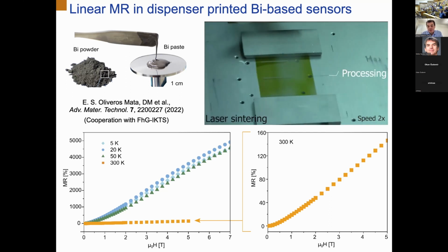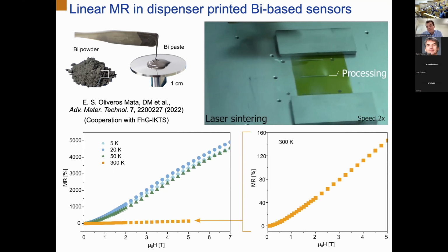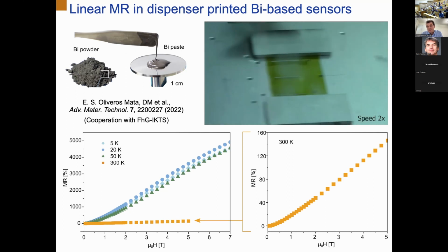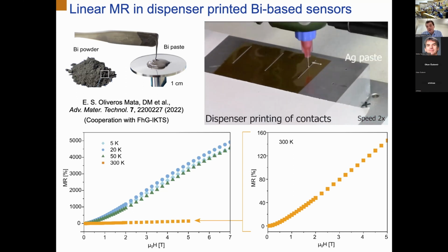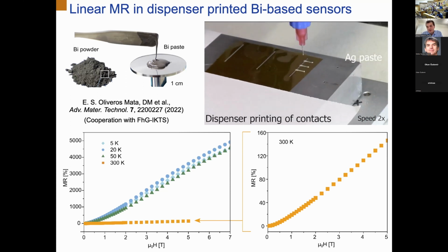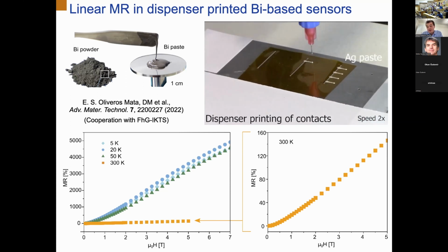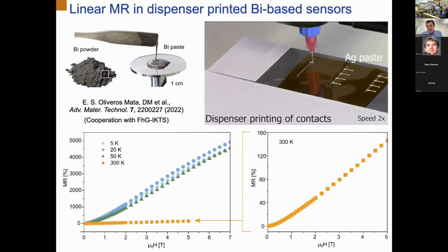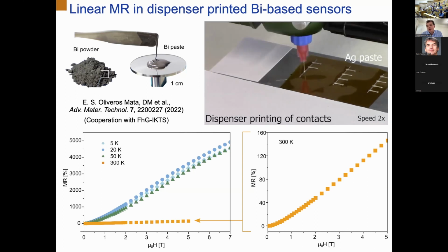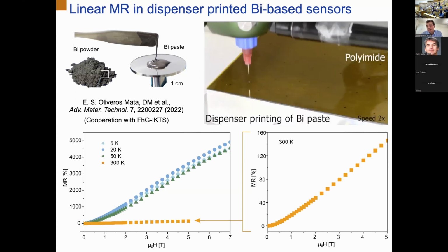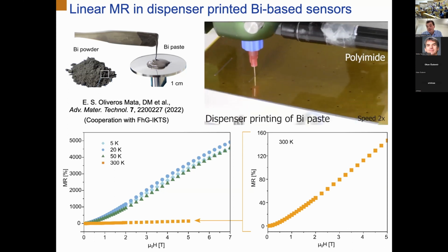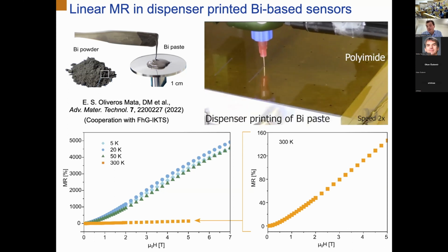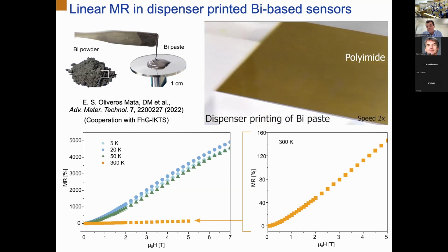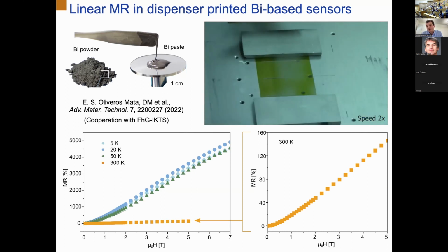If you have a look at the bottom of the slide, you see the characterization of these sensors. In this case, we use bismuth. It's not really a magnetic material, but bismuth is a very special type of material. It's a higher-order topological insulator. It has a very interesting band structure, which allows you to have quite a large magnetoresistive effect. And what is interesting about this effect is that it's a linear magnetoresistive effect. It means that if you increase the field, the magnetoresistance at high fields will behave linearly. Like, for example, we know that these sensors do not saturate their response up to 40 Tesla.